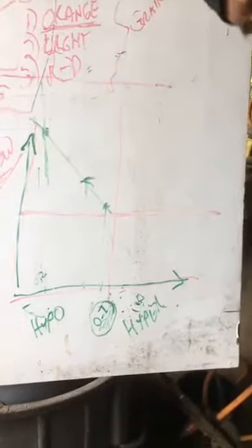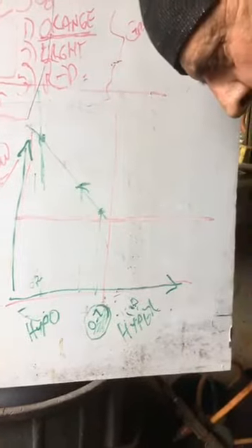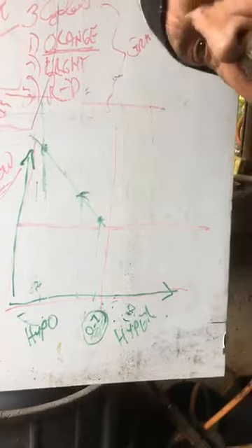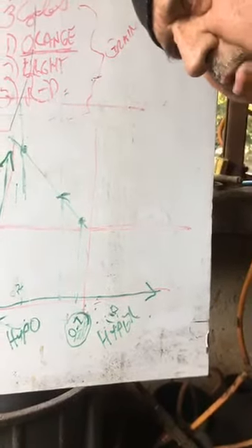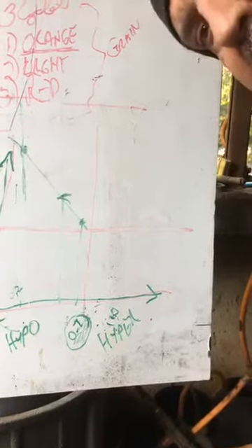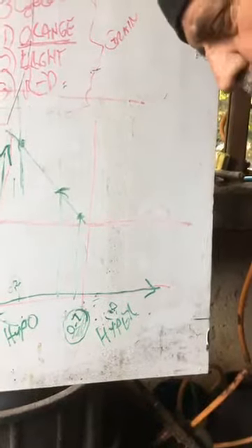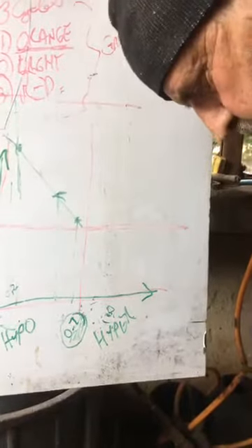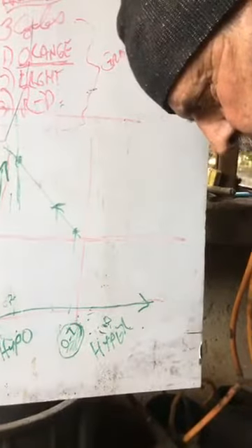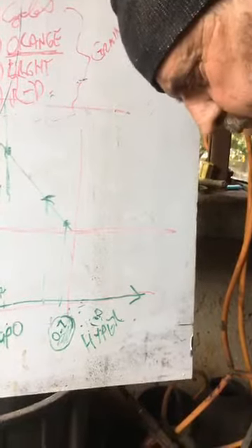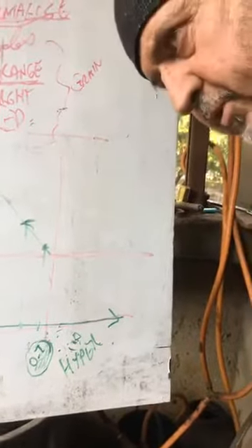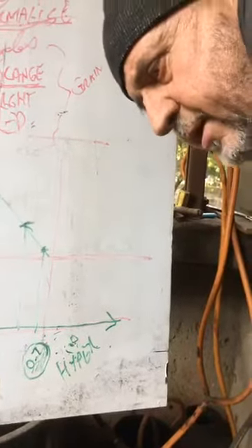Sorry, Johan is asking, do you cool the blade in water between tempering cycles? Yes, just under the tap water, cold water in the tap, in the sink. So cool it down and then back in again. Gerald wants to know, how long will it take in the forge for the grain to grow big again after reaching austenite stage? It's if it gets too hot. So if your forge is running at a nice even temperature, then you don't have to stress too much. But it's a good idea not to leave it in there too long. You don't want it to soak.